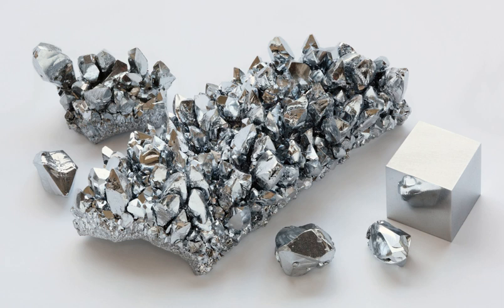Metallurgy. The strengthening effect of forming stable metal carbides at the grain boundaries and the strong increase in corrosion resistance made chromium an important alloying material for steel. The high-speed tool steels contain between 3 and 5% chromium. Stainless steel, the primary corrosion-resistant metal alloy, is formed when chromium is introduced to iron in sufficient concentrations, usually where the chromium concentration is above 11%. For stainless steel's formation, ferrochromium is added to the molten iron.